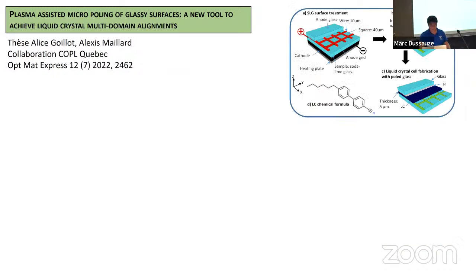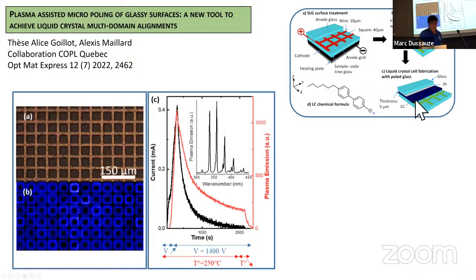So let's go now to how we can control this. Alice has tried to control this very well. She was using not strings, but grids. After making the plasma, you take the glass, and then you create your liquid crystal cell. If you use a grid with the proper poling parameters, you have a very well controlled plasma emission, as you can see, that follows very well the electrical current curves.